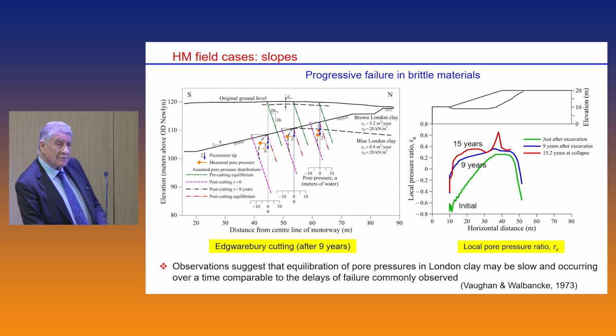But doubts on these mechanisms were first cast by the observations of Vaughan and Walbancke, who measured pore pressures in cuts in London clay, the ones that had not failed, and they found that the pore pressures they were measuring were actually quite far from equilibrium. And in fact, the times required to reach equilibrium were of the same order of magnitude as the times of failure recorded after the excavation. So they say that the observation suggests that the equilibration of pore pressures in London clay may be slow and occurring over a time comparable to the delays of failure commonly observed.